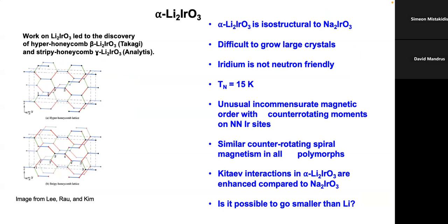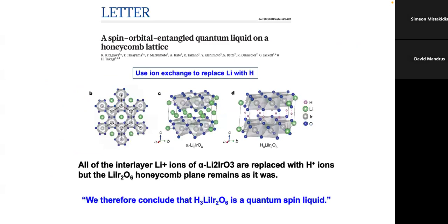And so the next iteration of this was, we can go even smaller than lithium, we can use hydrogen. And they did. So this guy named Hideo Takagi, who's in Germany now, was able to replace lithium with hydrogen, and it formed a pretty good spin liquid, with the caveat that this is a very disordered material. Because it's disordered, a lot of people don't really love it, right? Because the problem with disordered materials is that the neutron scattering on a disordered material can mimic a lot of the characteristics of the spin liquid.